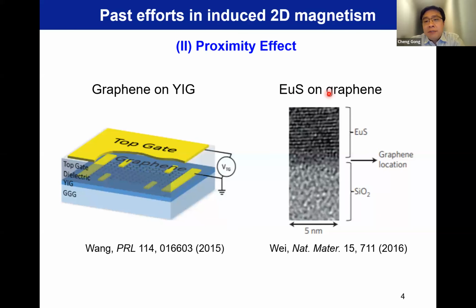The second way is a very smart method using the magnetic proximity effect. Basically, for whatever non-magnetic 2D materials, if you can prepare them together with a traditional magnetic thin film with a clean interface, by large chance you can use the interfacial spin wave function overlap to magnetize or spin polarize the electrons in the originally non-magnetic 2D materials. This is almost a universal way to induce spin polarization in non-magnetic 2D materials. This is an extrinsic way. We certainly know, for example in graphene, the magnetism does not directly originate from the exchange interaction in the pi electrons of graphene. That's not the case. And for device application, you probably need to carry the whole stack to fabricate the devices.